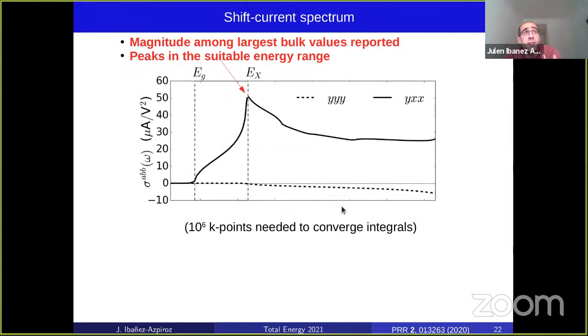Now, we have applied our formalism for calculating the shift current, and we show here the two conductivity components that are allowed by point group symmetry, YYY and YXX. The first one is fairly small, while the other one starts to grow right from the bandedge and reaches a maximum at around 1.3 eV. Now, this value is very large. This magnitude is among the largest bulk values reported in the literature and peaks in a suitable energy range for some potential applications. So in this sense, this material can be interesting.